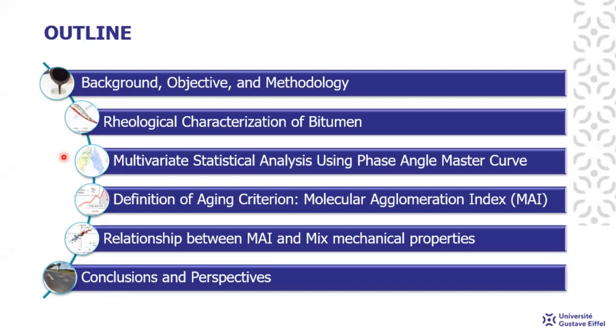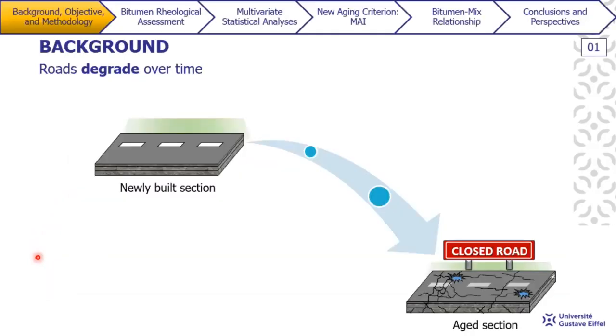So we decided to apply multivariate statistical analysis to further investigate phase angle master curve. And with the findings of this analysis, I could come up with a criterion that I use to track bitumen aging, named molecular agglomeration index, or MAI. Then I present the relationship of this new criterion with some asphalt mix mechanical properties, and finally some conclusions and perspectives for future work.